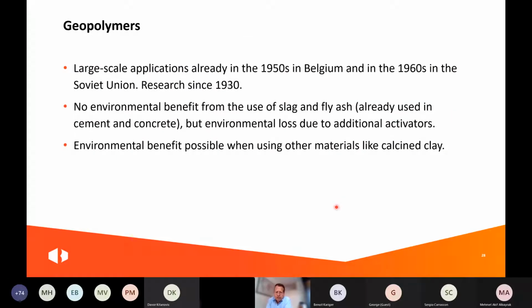So geopolymers were already used in the 1950s. But important, if you use slag and fly ash, they are already used in concrete or in cement, then you don't have any environmental benefit, but only a replacement of the use. And actually you have an environmental loss because you have the additional activators you have to use with a high CO2 profile. So if you want to have an environmental benefit, you need additional sources of materials that are not currently used in concrete, like calcined clay or perhaps fly ashes that are not suitable for regular concrete.